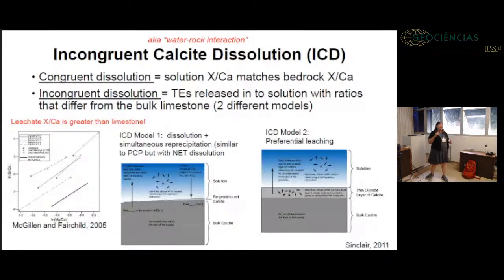The other model for ICD is a little bit more complicated, and it involves dissolution of the limestone that's almost simultaneously occurring with calcite reprecipitation. So in this model, you have this bulk calcite, and you're dissolving it, and the dissolution itself may initially be congruent. But then you have this reprecipitation, and the magnesium-calcium ratios in the reprecipitated calcite are going to be set by the solution composition as well as that distribution coefficient. So you're going to effectively have a PCP-like signal. The more of this that occurs, you're going to increase the magnesium-calcium and the strontium-calcium in the remaining solution.